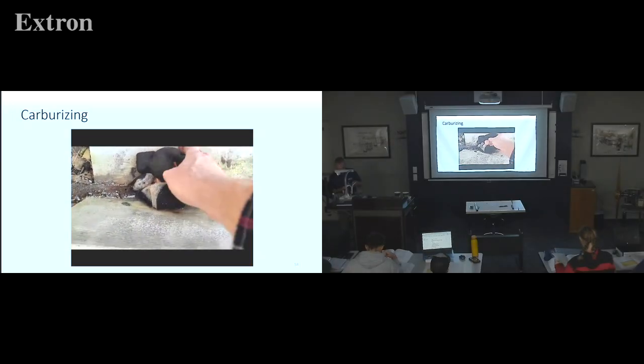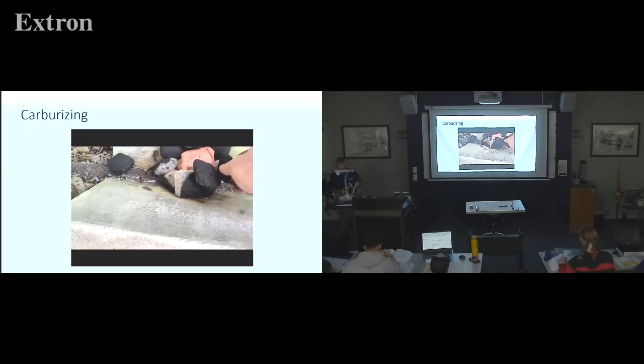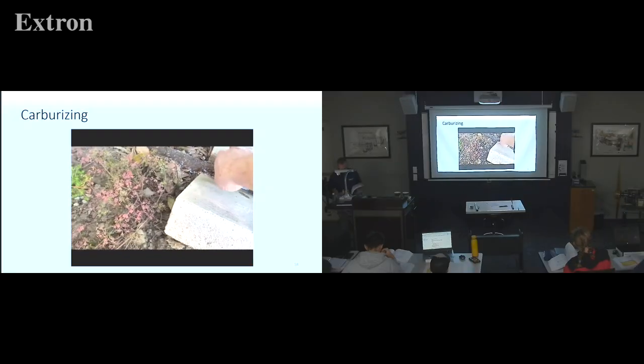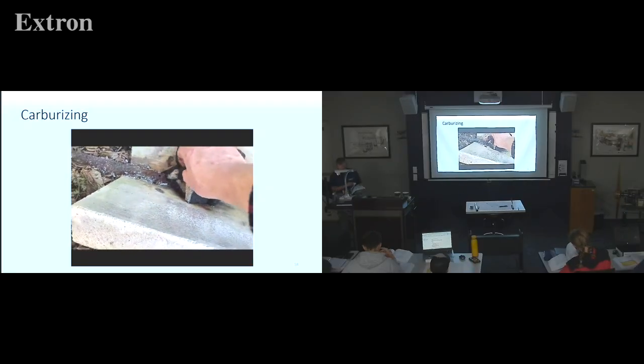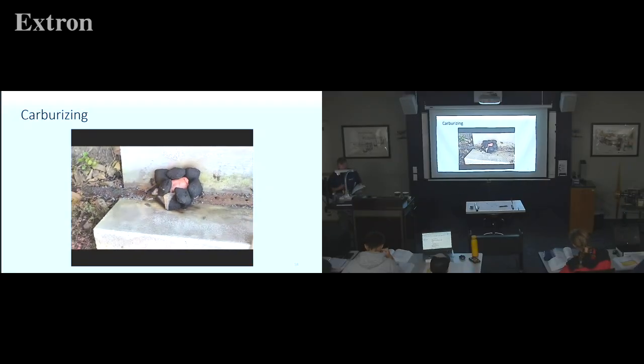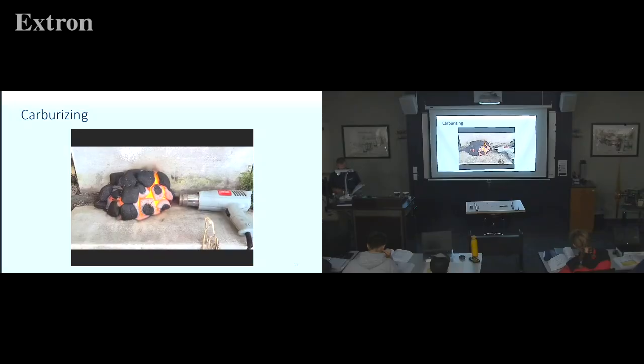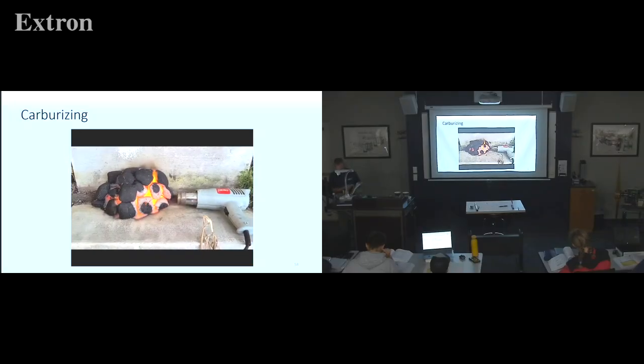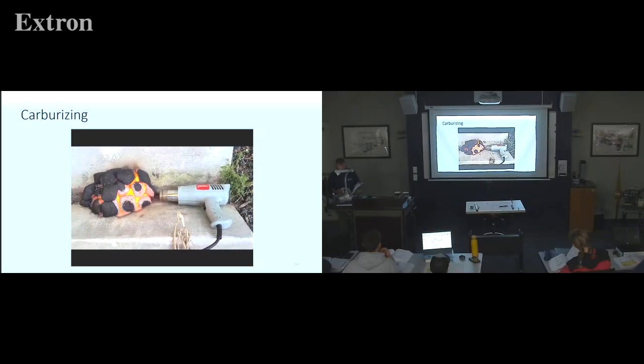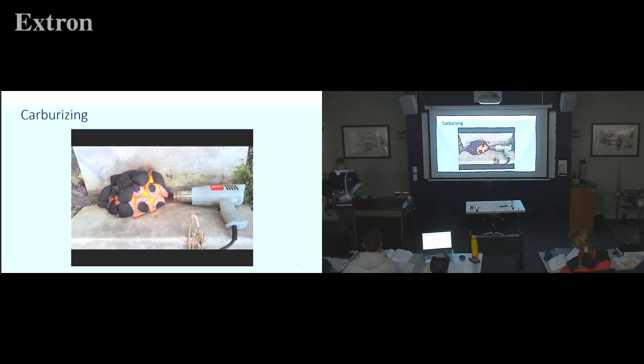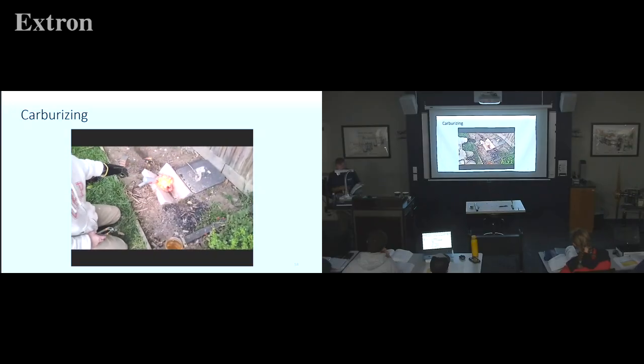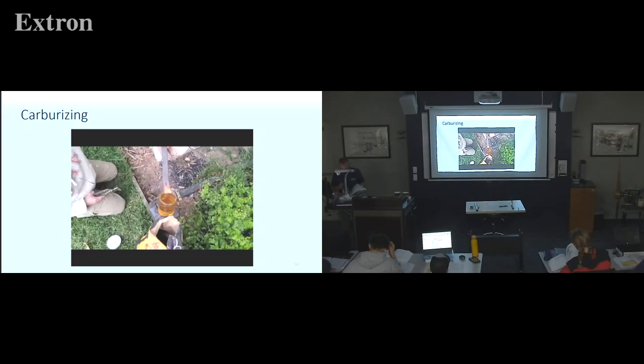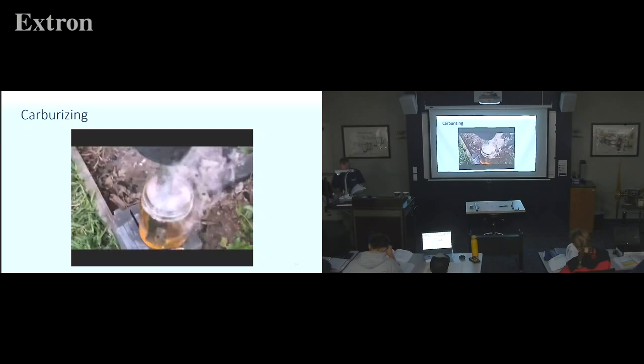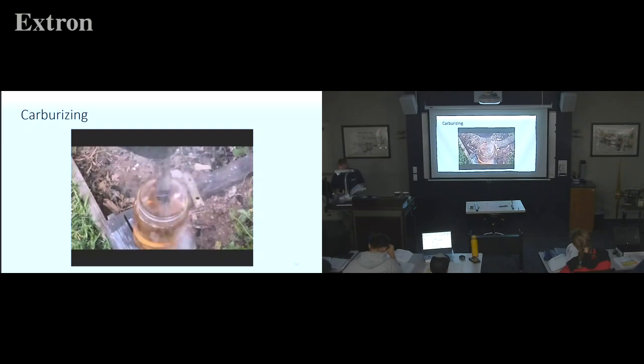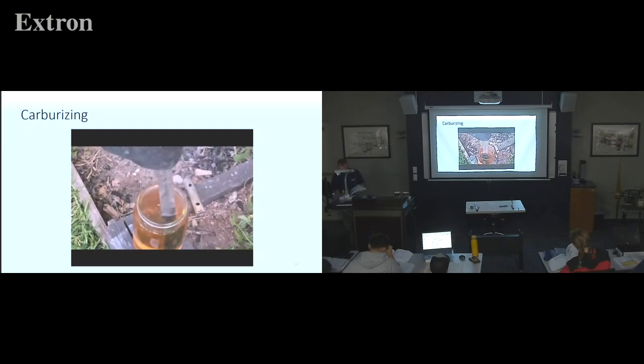The clay was fast drying, so it just needed a few days to dry, and then I put it into my simple backyard forge, surrounded by some charcoal barbecue bricks. Then, with the addition of some forced air, I left it to cook at high heat for around 2 hours to hopefully absorb those carbon atoms. Before quenching, I warmed up the oil a little, using a hot piece of steel to ensure it was viscous enough to cool our samples properly, which is something else I learned from YouTube.